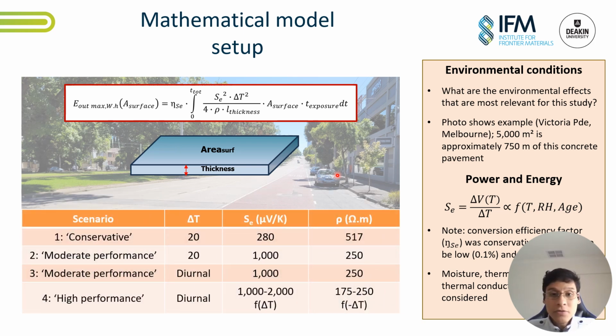Based on all these variables together, we created 4 scenarios. The first one, conservative: constant temperature gradient, low Seebeck coefficient, and high electrical resistivity. The second one, we want to evaluate the impact of the Seebeck coefficient and electrical resistivity. So we use the same temperature regime as the first one, but increase the Seebeck coefficient and reduce the electrical resistivity. The third scenario, we actually want to see the impact of the temperature. So we keep the Seebeck coefficient and electrical resistivity, but change the temperature regime to the second one, which is variable. And the fourth one is a much more realistic scenario, in which the temperature varies with time, along with the Seebeck coefficient and electrical resistivity, which do as well, as a function of time and temperature.